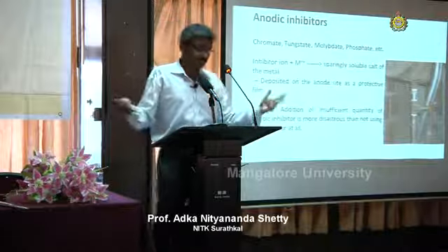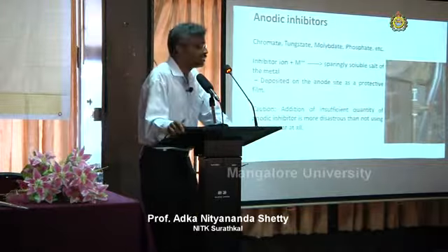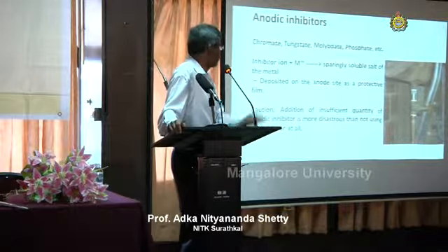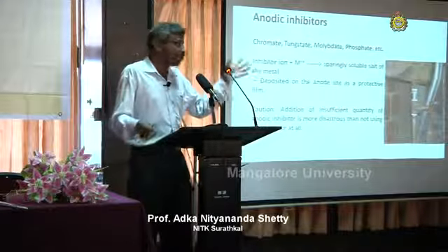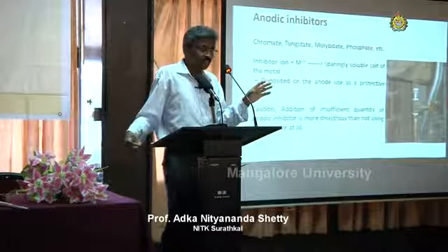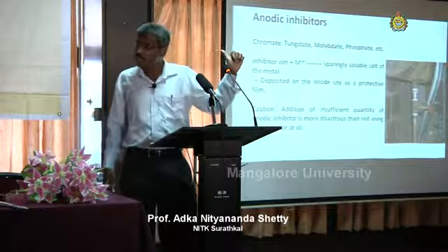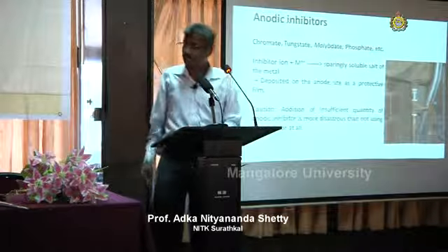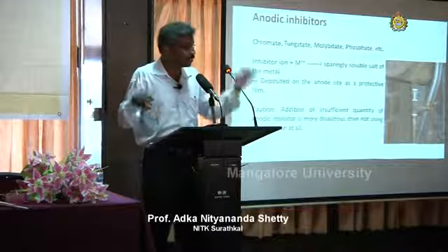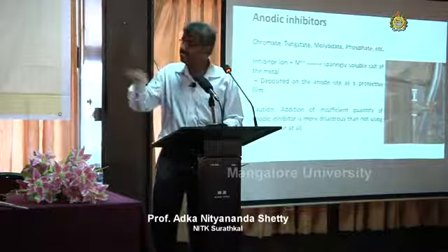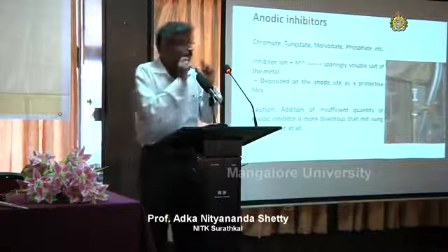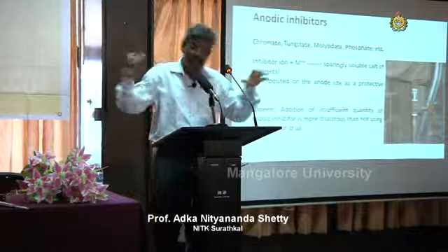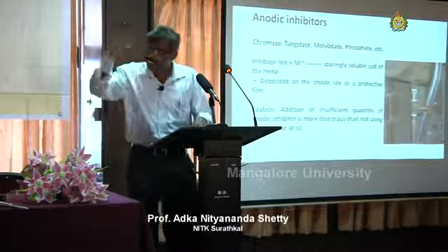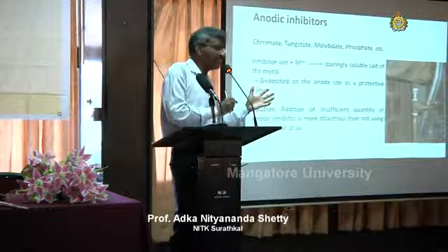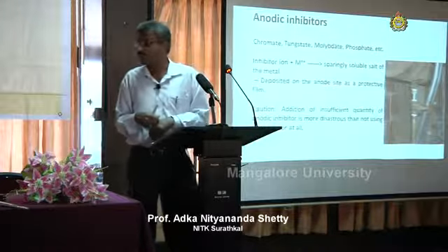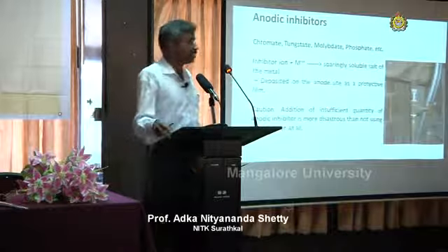Anodic inhibitors: the commonly used inhibitors are chromates, tungstates, molybdates, phosphates. The mechanism of their action is, at the anode, metal is converted into metal ion during corrosion. These metal ions will combine with anions like chromates, tungstates, molybdates, and form their respective salts. For example, if it is iron, they will form iron chromate, iron tungstate, iron molybdate, and these salts will deposit on the metal surface, forming a protective film. It will be a continuous film on the metal surface, acting as a barrier between the underlying metal surface and the corrosion environment, or they prevent the corrosion environment from coming in contact with the underlying metal surface and thereby reduce the anodic reaction. Next slide, please.